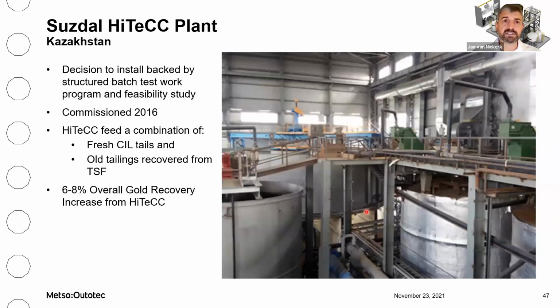The second installation was in the Suzdal plant in Kazakhstan. And they decided to install the process after a structured process of batch work that was done on site by them and then backed by a feasibility study. The plant was commissioned in 2016 and again treats a combination of fresh CIL tails as well as old tailings recovered from the tailings storage facility. And they can see an increase of between 6 and 8% overall gold recovery due to the addition of the HiTeCC process to their circuit.